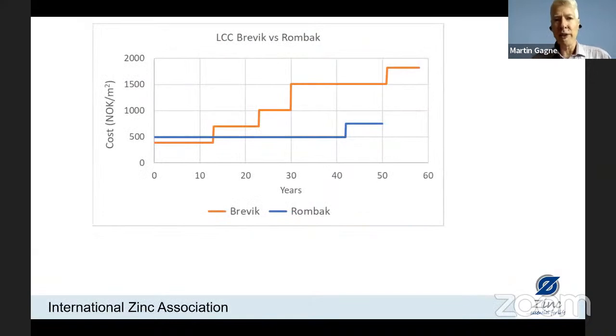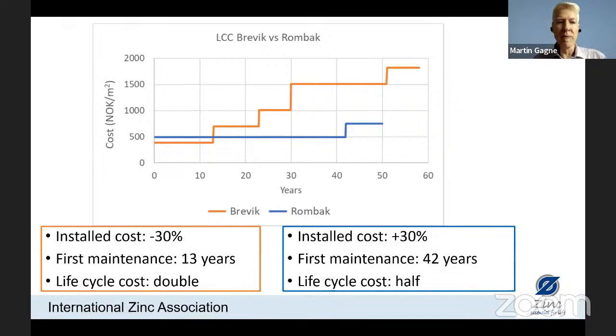Now, we can look at the maintenance cost for these two bridges to get an idea about life cycle costs. So the Brevik Bridge is in orange and the Rombak Bridge is in blue. If we look at time zero, we can see for the Brevik Bridge, it was 30% less to paint that bridge compared to a duplex coating. Although we had the first paint maintenance of that alkyd paint after 13 years. So after 13 years, the duplex coating became cost effective.